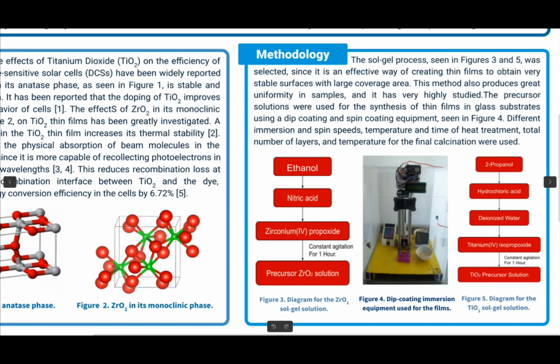There are various methods to synthesize these solar cells, but Sol-Gel is often used because of the surface and texture of the thin films generated by this method, which allows for great uniformity of samples. Sol-Gel consists in the formulation of a solution from a precursor substance mixed with an acid to modify the metal ion. As seen in figures 3 and 5, the zirconium dioxide sol was created by mixing zirconium 4-propoxide with nitric acid and ethanol for an hour, while the titanium dioxide sol was generated from a titanium 4 isopropoxide with 2-propanol and hydrochloric acid, diluted with deionized water.